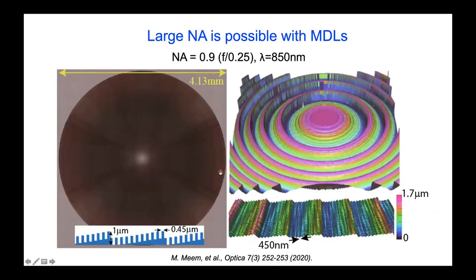So I'll show you a few more examples. It is possible to get very large numerical apertures using these approaches. This is an NA 0.9 lens designed for 850 nanometers, with a diameter of 4.13 millimeters. And it had some interesting hierarchical structures with relatively small teeth sitting on top of relatively large structures, as you can see also here. And these were fabricated in the advanced research labs at Heidelberg, actually, in Germany. And you can see they're pretty challenging to make from a grayscale perspective. But in principle, once you make it, you can use this as a master mold for replication using imprint lithography.